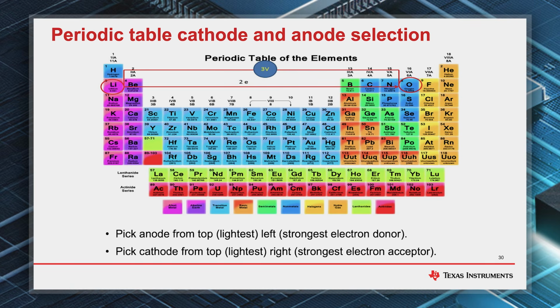And I'll show in a few seconds actually a whole plot of different energy densities. But what is the next best thing? Let's say oxygen is difficult because you have to catch it from the air. So sulfur actually is another promising candidate because it is right under the oxygen and still quite light. And it is also very abundant. Sulfur is available as a waste product of the energy in the oil and gas production industry in huge amounts. On the other hand, sodium, I already mentioned, is right there below lithium. So sodium is also quite a good material, maybe not for the highest energy density, but for being much more abundant than lithium.